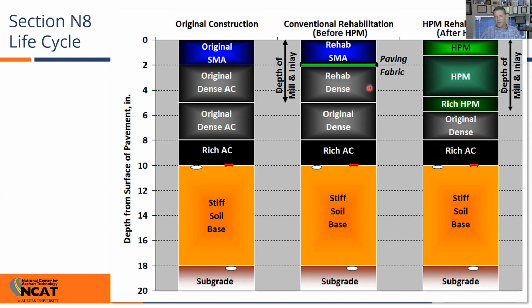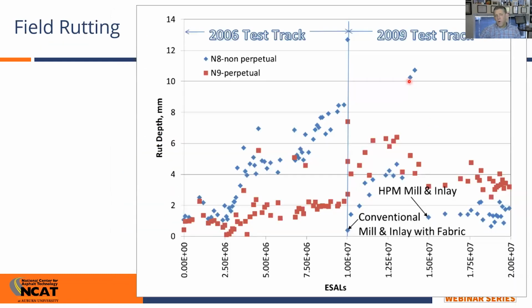So we milled out a little bit deeper than what we had originally, and then put in these high polymer mixes. And it was pretty remarkable what we saw in terms of performance. This is rut depth versus ESALs. So this is the first test cycle to 10 million, and then the second test cycle to 20 million. Just for comparison, the 14-inch perpetual section did just fine over the 20 million, which we expected. But the non-perpetual, in the first 10 million, we were up at this rutting failure point.